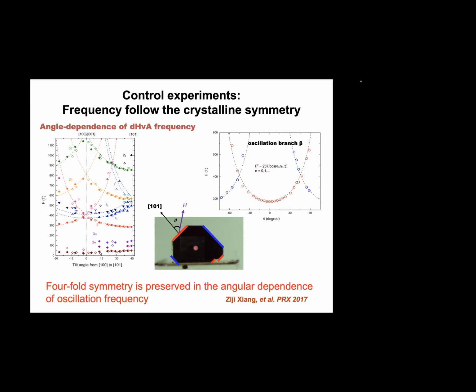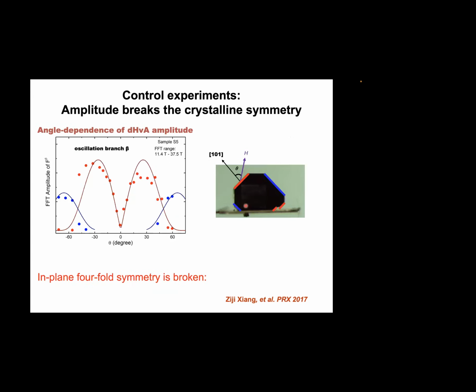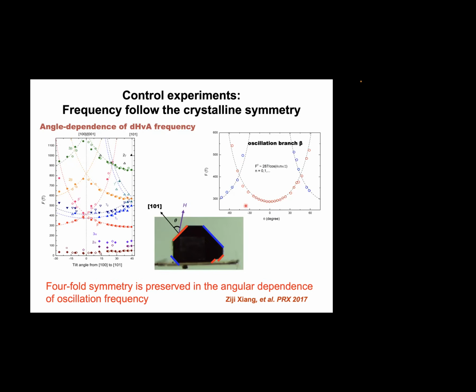One direction versus the other direction. Could I have a question? Could I interrupt you? So I think the important fact is that surface states don't have just one Dirac cone, but they have three Dirac cones, and two of them are displaced in energy. Right. So in some sense, when you cut, you have not just one watermelon, but one large watermelon and one small one. Does it mean that when you address oscillations, you're supposed to have two periodicities given by the size of the large and small watermelons?